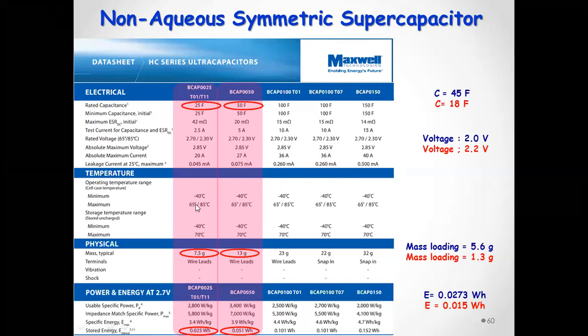If you see, for 25 farad capacitors, they use 7.5 grams of active material. For 50 farad, they use 13 grams of material. If you see the stored energy in this case, they have 0.0025, that means 25 milliwatt hour. In our case, we have 30 milliwatt hour and 15 milliwatt hour, for example in the case of the 45 farad and 18 farad capacitors we have fabricated. In the case of 45 farad, we use only 5.6 grams. If you compare with their 50 farad capacitors, they are using 13 grams.